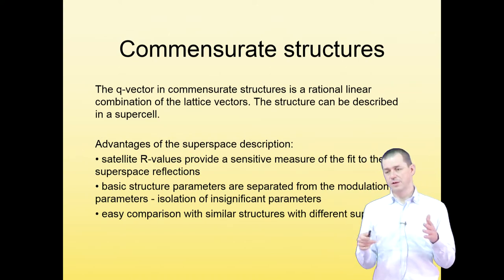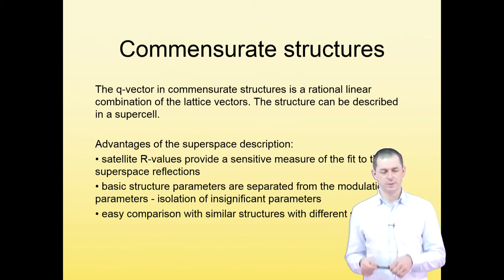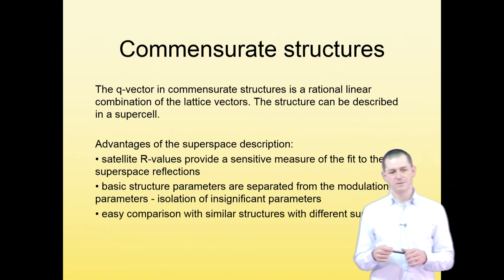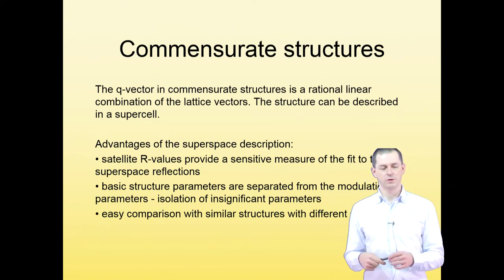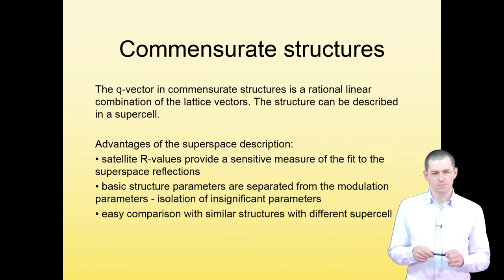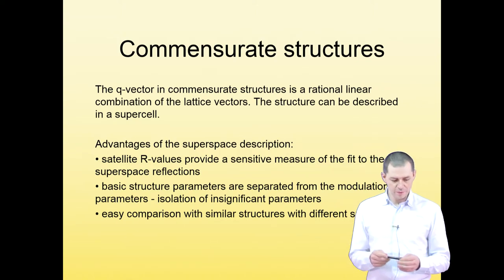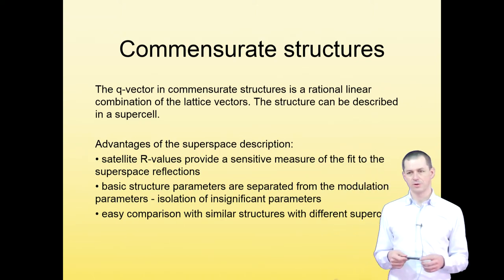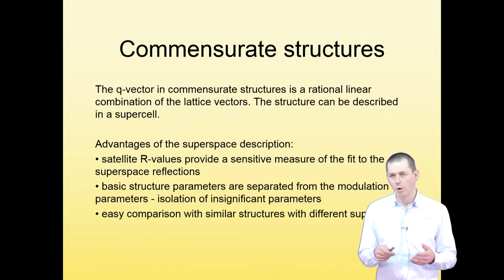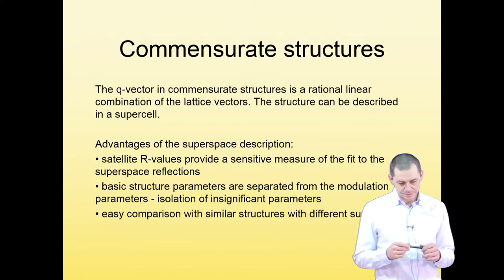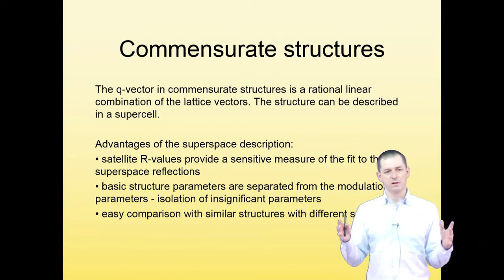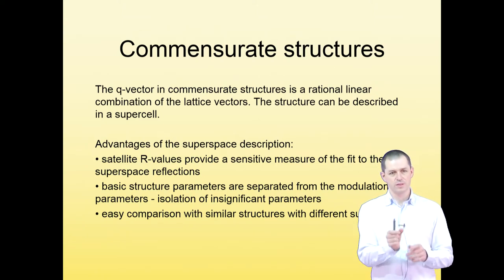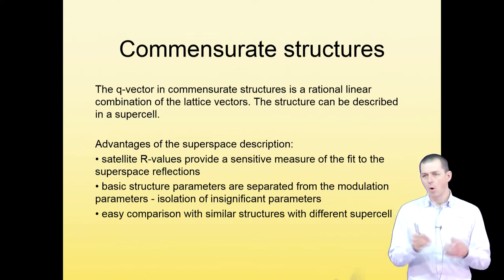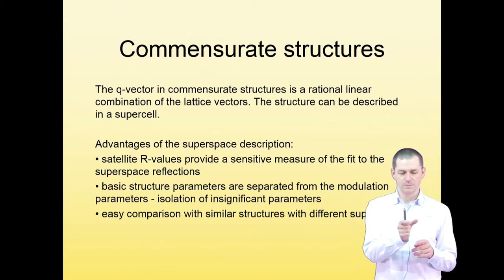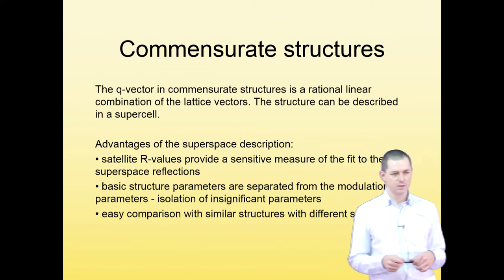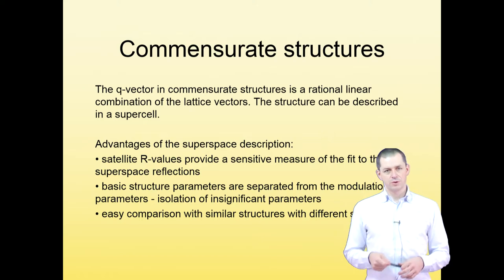However, if that rational number is complicated, like 27 over 49, that is such a complicated rational number that practically this is irrational, and we can treat it as irrational. However, sometimes the modulation vector is clearly rational and it has components like 1/2, 1/3, or 3/5. And in that case, you can always find a supercell in direct space or a subcell, a smaller cell, in reciprocal space, which describes all the positions, so which describes satellites as well as main reflections on the same cell. And then you can describe the structure in the supercell.